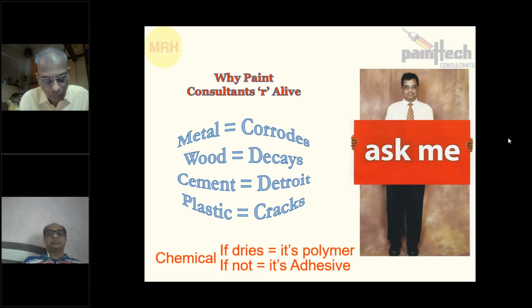Last point - number 4: no hard water should be used. And lastly, DM water is the best. If you use demineralized water, results are excellent. You can go up to 15% water without any additive. And surprisingly, with DM water, we don't get blisters even without adding an anti-blistering agent, even in hot sun.